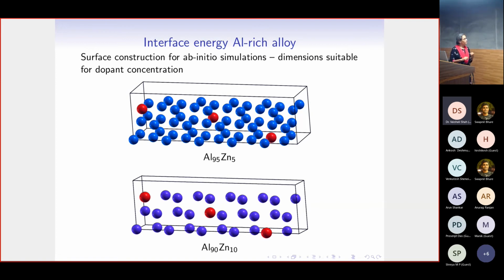Okay. So what we do is we take the correct orientation of the surface that we are interested in. So we start with the pure aluminum surface structure. And in this, we find out what would be the suitable number of repetitions for the unit cell that we need to work with, so that we are able to get the correct dopant concentration. Okay, and accordingly now we build the surface. So this is now the smallest unit cell for the aluminum 95 zinc 5 surface that I can work with, and this is the 60 atom unit cell. And in this 60 atoms, we have doped 3 atoms with zinc. So that gives me the correct dopant concentration.